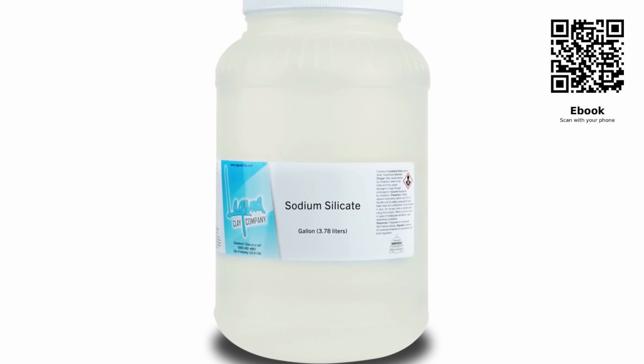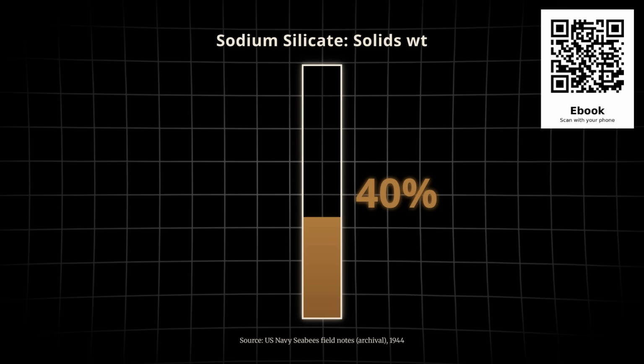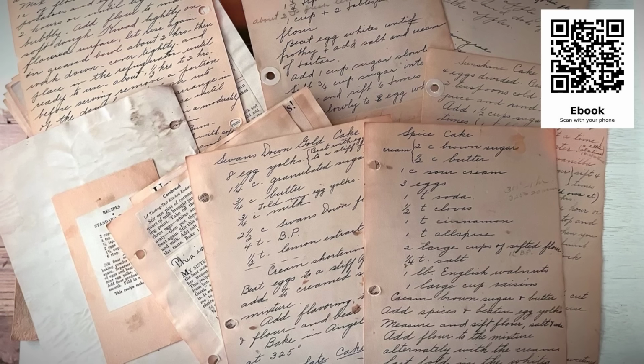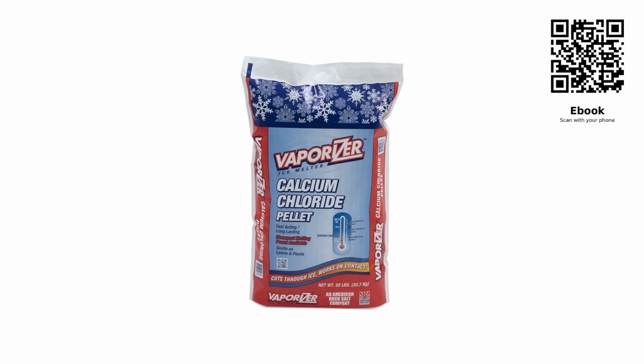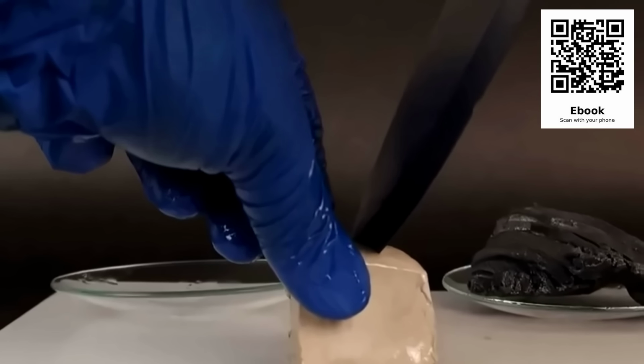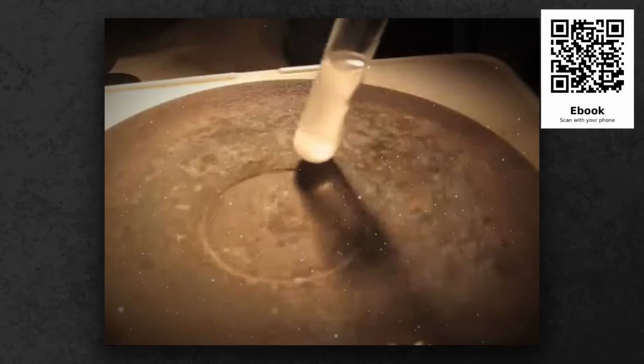If you are buying from a chemical supplier, ask for N-grade or 3.22 ratio sodium silicate solution at approximately 40% solids by weight. That is the industry standard, and that is what the historical Amish recipes correspond to most closely. For the setting agent, you have options. Calcium chloride, the same chemical sold as ice melt in winter, works well at about 2% by weight of the silicate solution. It accelerates the cure dramatically and produces a strong, dense matrix. Sodium bicarbonate, which is baking soda, works more slowly but is gentler and easier to control.